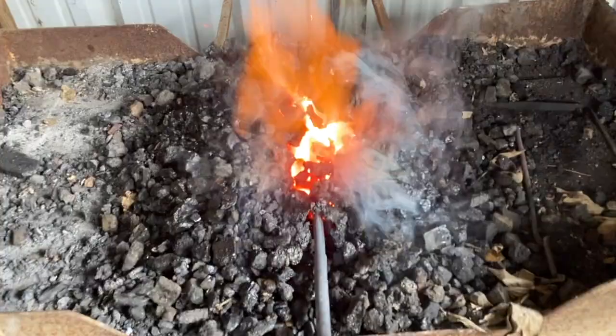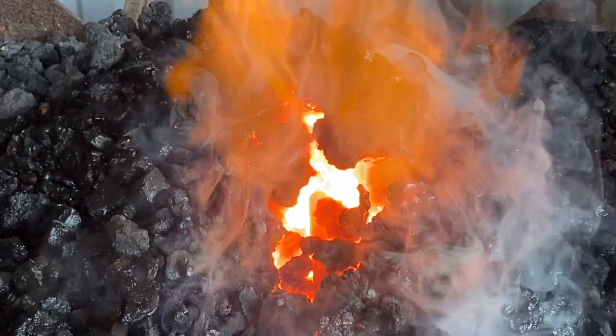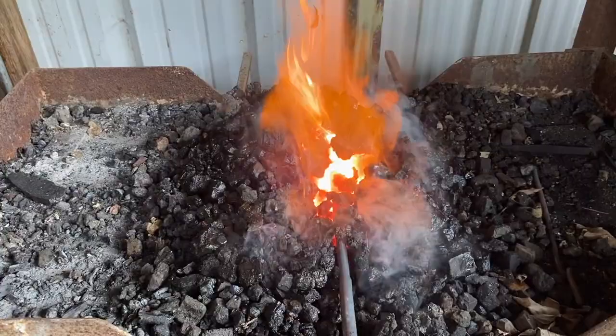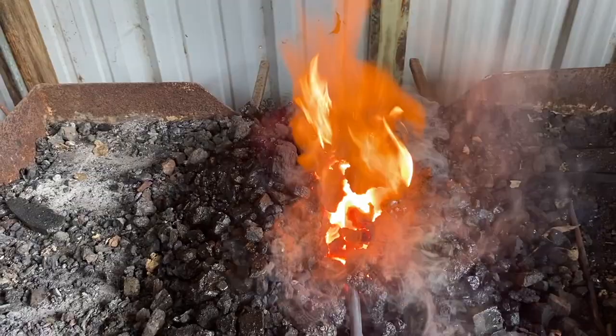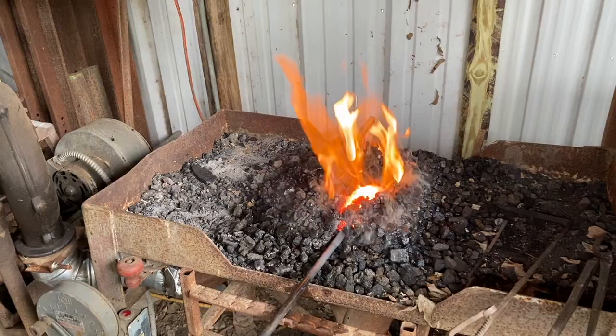So that is a very efficient way of forging. The steel appears to be hot. It's glowing orange. That orange temperature tells me it's around 2,000 degrees. That 2,000 is a good temperature for forging. Much hotter than that, you're going to get a lot of grain growth. You're going to get close to the melting temperature, 2,300, 2,400 of medium and hot carbon steels. So this is just a good temperature. The steel is nice and soft.